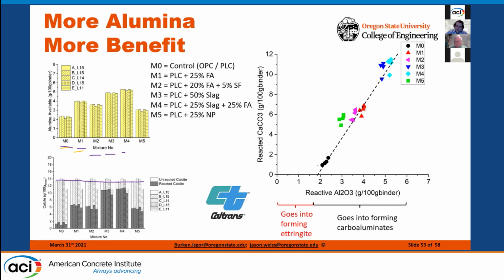And if we look at this plot on our right-hand side, the more alumina you have in the system, the more it's going to react with the calcium carbonate, the more it's going to form those carboaluminate phases. Now, if the limestone doesn't react, it's going to stay as a powder. It's going to stay as a solid product in the system. But if it does react, it's going to actually help us. And here you can see the most reactive of all these phases are the ones that are actually containing slag in the overall system.